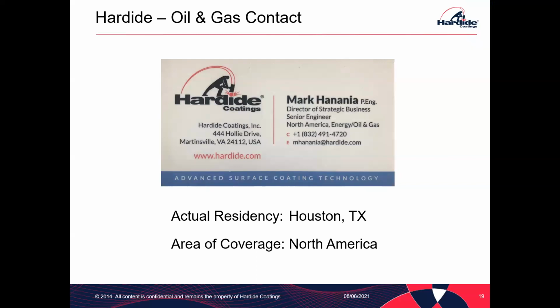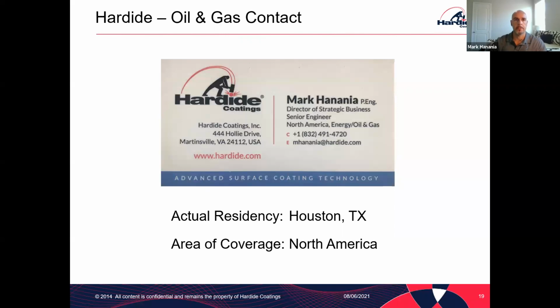Mohammed has another question. Do you need to do a holiday test? Not quite sure what that is. A holiday test is to see if there are any defects afterwards. Typically not. Initially we verify the dimensions of the part based on the drawing. Then we check the thickness of the coating that we apply to make sure that we hit the target and are within spec. But it's very easy for us to identify if the coating didn't work out, and if that is the case, we can strip and recoat. So there are methods for us to inspect and verify the effectiveness of the coating, and also hardness as well.